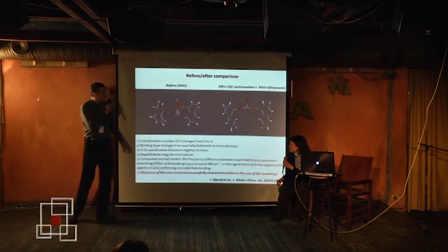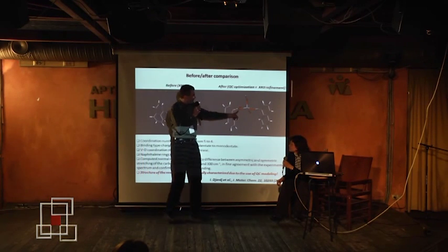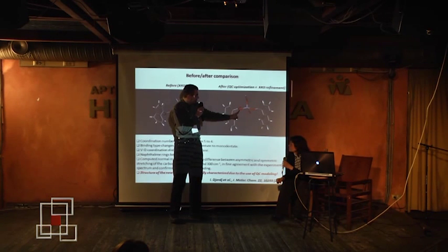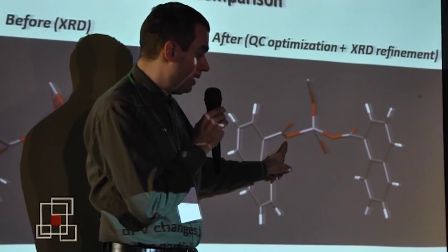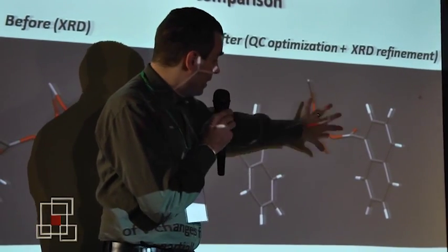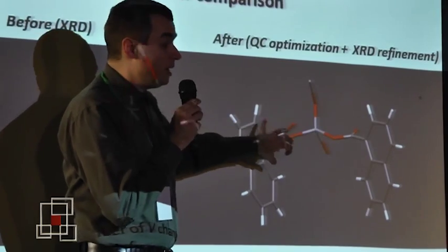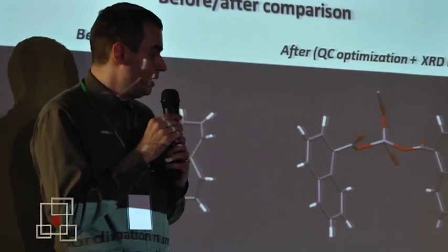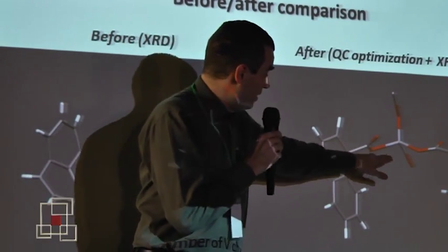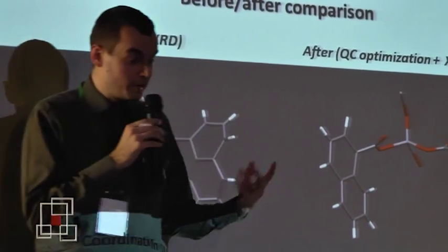We also see that the binding of the carboxylate group goes only through one atom, the oxygen atom, which means it's monodentate, not bidentate. And the calculation of frequencies was in very good agreement with the experimental infrared spectrum, so the type of binding shown in this picture was further confirmed.